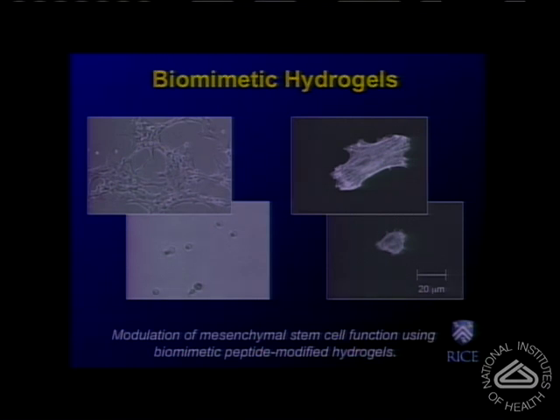Here we have an example from our collaboration with my colleague at Rice, Cindy Farach-Carson, that involved the isolation of a 15 amino acid peptide from osteopontin, the covalent conjugation of that peptide within the bulk of a biodegradable polymer scaffold, and the culture of mesenchymal stem cells and other cell types, including fibroblasts, on the surface of these materials. And what we found was we can create an environment that is conducive to the adhesion and migration of bone cells or bone progenitor cells, but not fibroblasts. And that can be an ideal material for guided bone regeneration for dental applications.